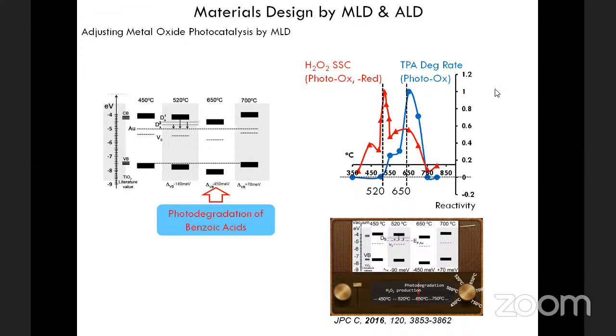So we did a quite thorough analysis combining different spectroscopies. One of them I show here, and we studied the band gap and band alignment evolution of the oxide with anneal temperature. And what we found out is that when we anneal this material at 650 degrees Celsius, both conduction band and valence band have a very significant downshift, specifically with the valence band downshift of 450 milli-electron volt, as you can see here.